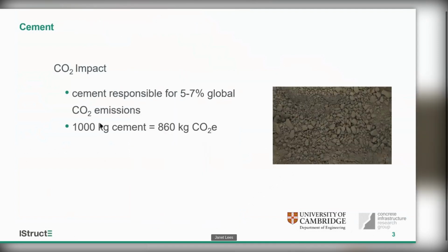So just as a quick recap, the CO2 impact of cement is responsible for 5 to 7% of CO2 emissions, and that's connected to the fact that we use very large volumes of it, and approximately 1,000 kilograms of cement is about 860 kilograms CO2e.